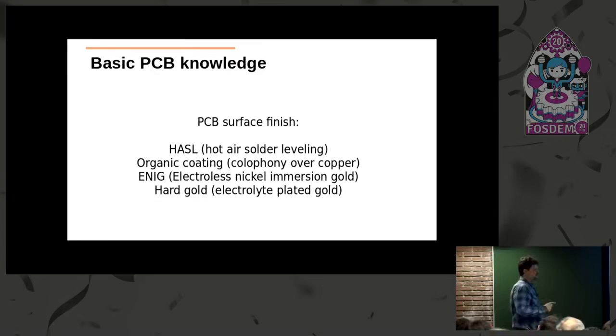And organic coating is a very cheap way to preserve PCB copper. It has excellent solderability. Everything is cool, but it is not very durable. The PCB has to be soldered very fast. Otherwise, it will oxidize. And of course, electroless nickel immersion gold. This is the best plating you can have for your PCB to solder QFNs, BGAs, any kind of components. It's a very thin layer of gold over nickel over copper. And it's microns, it's on atomic levels. But the gold is a noble metal. It doesn't get in chemical reaction with the oxygen, with acids and all other stuff. So it preserves the PCB very well.